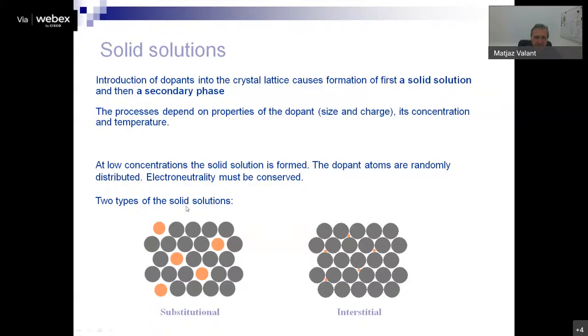Now, the extension of the solid solubility limit depends on the nature of the dopant, its size and charge. If the size is very different from the size of the parent ions or atoms, the solid solubility limit will be low. If they are more similar, the solid solubility can be very high. In some cases, it can be complete solid solubility from one end to the other, with the same crystal symmetry. I think this is often the case between metals. If we mix metals in any concentration, they will maintain the crystal symmetry. But of course, not all, just some very similar metals.